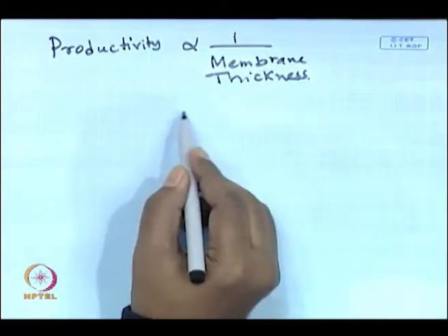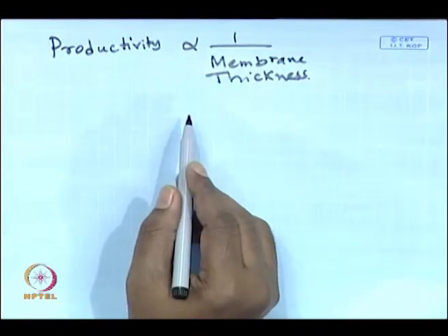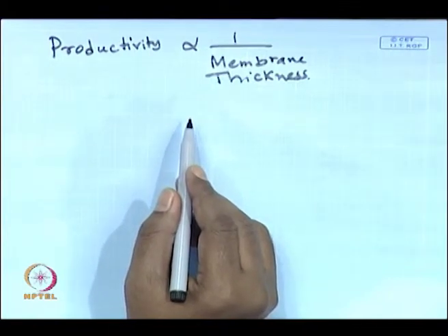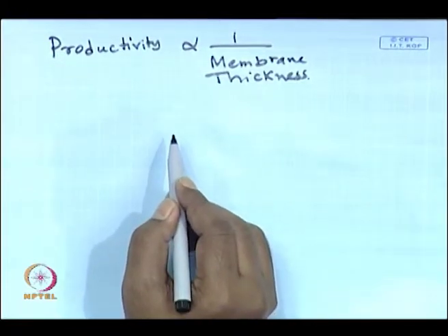First, on a non-woven polyester fabric, you put a coating of, let us say, polyacrylonitrile or polysulfone, something like that. So, these polymers will be cast as a film on the polyester fabric with, let us say, higher pore size. Then you cast another film of, let us say, cellulose acetate or polyamide over it. Basically, that will create a skin over the higher pore sized polymer support.